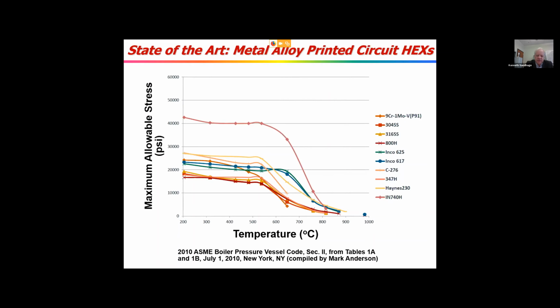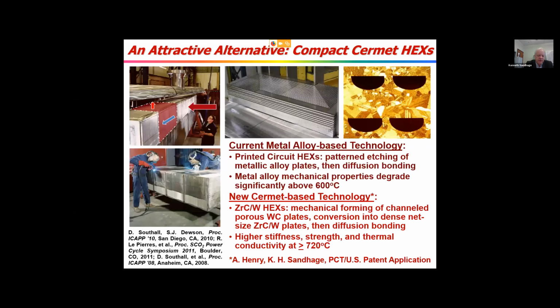So that by the time you get to 800 C, the maximum allowed stresses, according to the boiler pressure vessel code, are only on the order of 5,000 PSI or less, which is dangerously close to the operational pressures that one would like to use the supercritical CO2 at. So that's what drove Professor Henry and myself to look at other alternative materials, such as zirconium carbide tungsten.